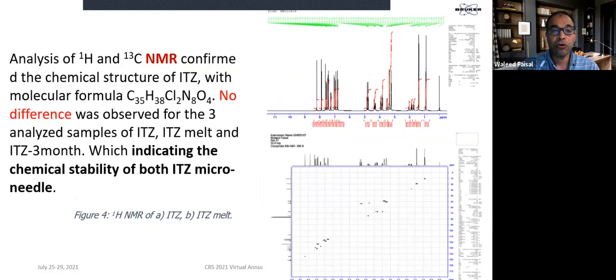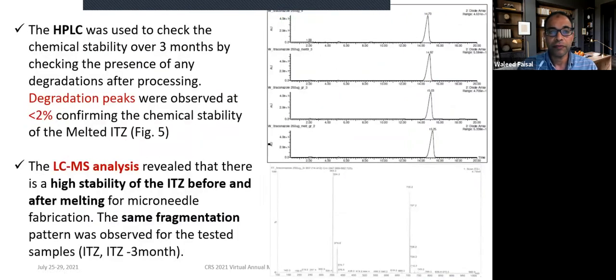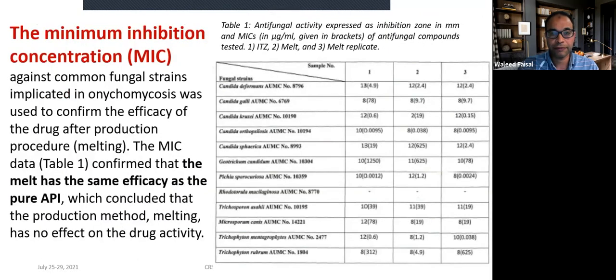The NMR also confirms that there is no difference observed between the itraconazole and its melt over 3 months, indicating chemical stability. The HPLC data confirms there is no degradation peak, and all that we observe is less than 2% degradation, which confirms the chemical stability. LC-MS analysis confirms the high stability of itraconazole before and after melt, with the same fragmentation pattern.